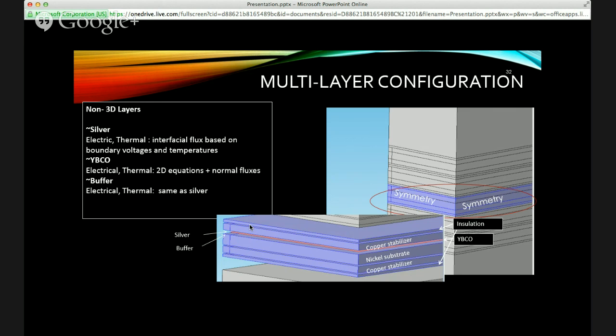Those inner layers, such as the silver and the buffer, surround the YBCO. However, they're not physically present, because they're thin as well, so they didn't need to be present. But in order to account for them, you looked at different interfacial fluxes to essentially create the layer using equations rather than physically having to mesh it.